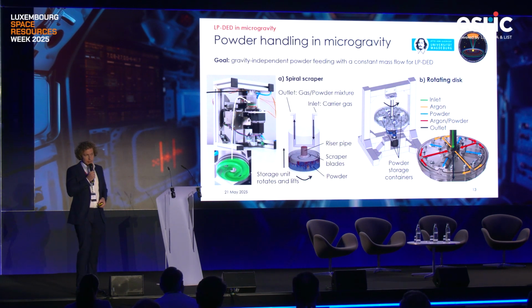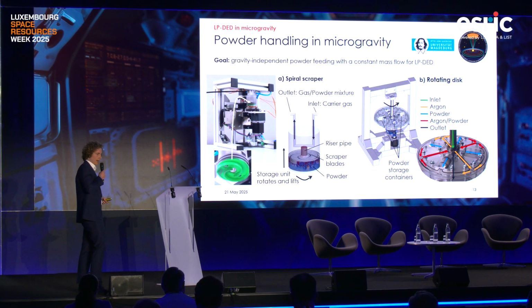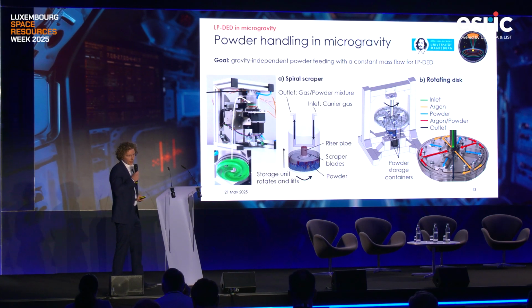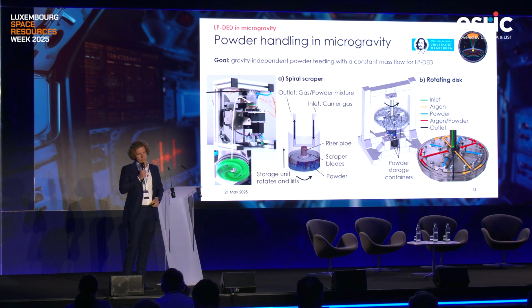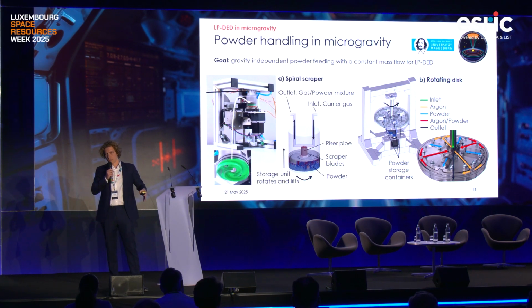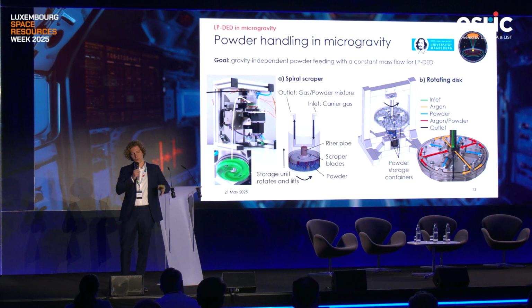The first one is a spiral scraper, where we have a powder container which could rotate and move up and down. And with the help of the Archimedean geometry, you can see in green in the left lower corner, if we are rotating this geometry, then the powder goes into the center, and then if we are moving it up, then we could catch the particles with the help of the argon volume stream.